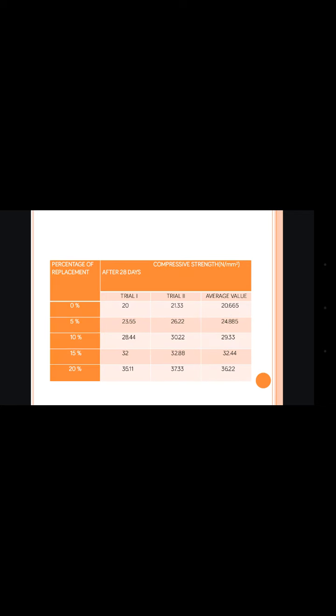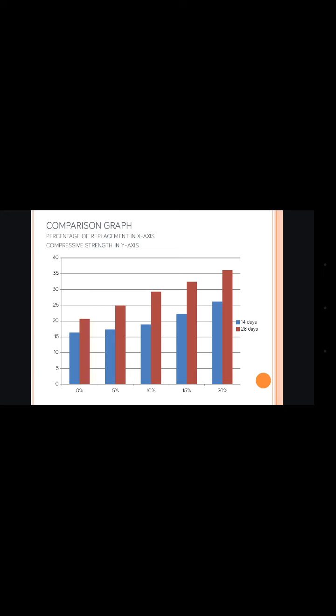And this is for 28 days compressive strength. In this case also, we find that the average compressive strength increases as we increase the percentage of e-waste incorporation in the concrete. This is the comparison graph. The blue ones are 14 days curing and the 28 days are the brown ones. We've plotted percentage replacement on the x-axis and compressive strength on the y-axis. We can find a steady increase of compressive strength.